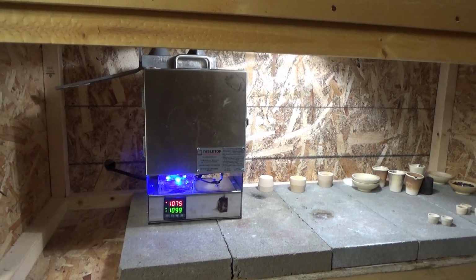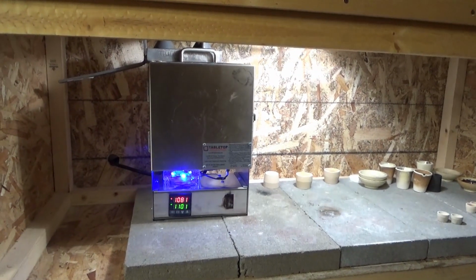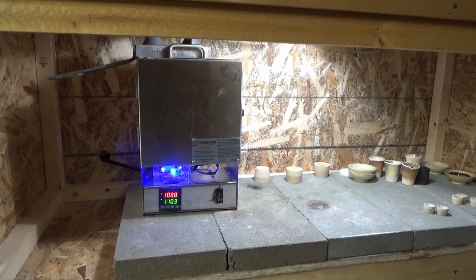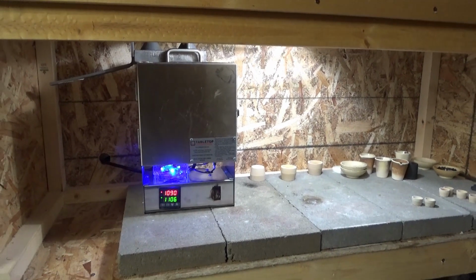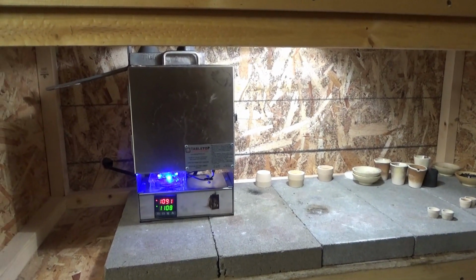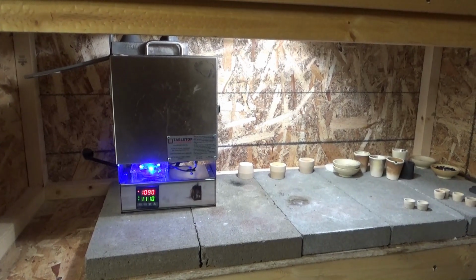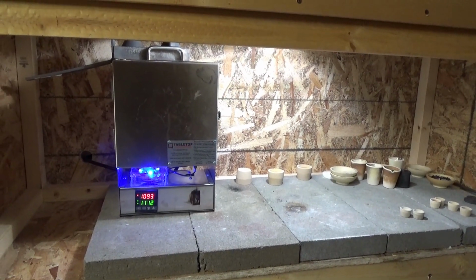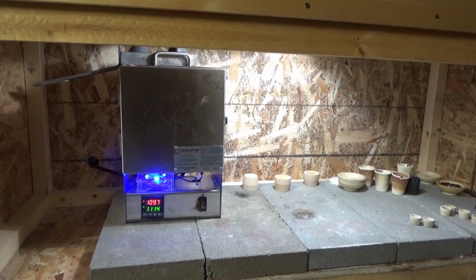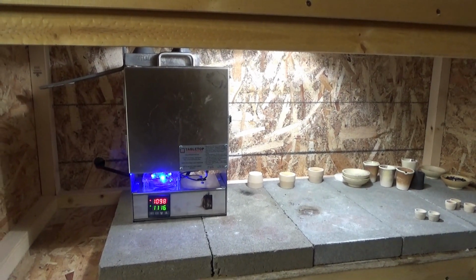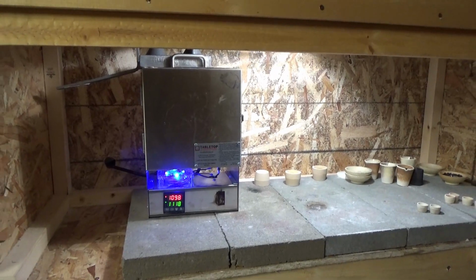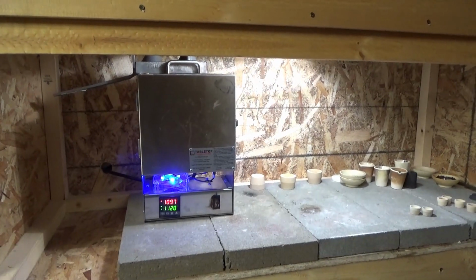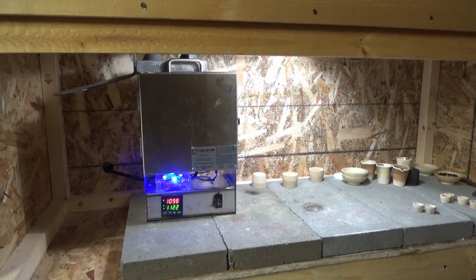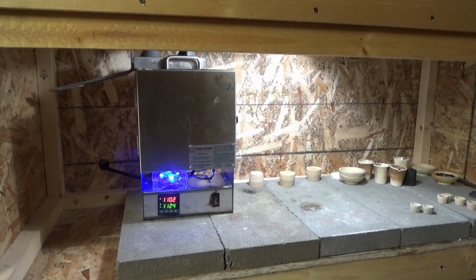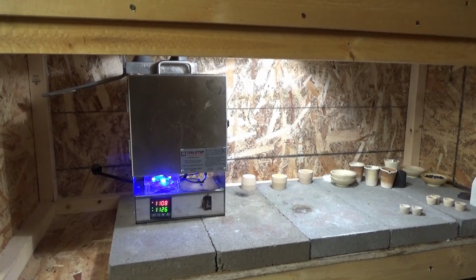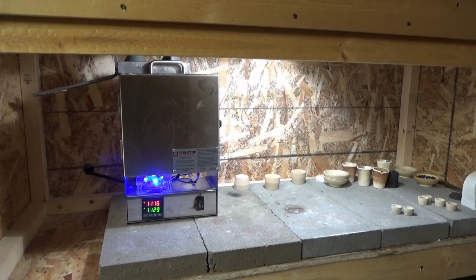And then there's the energy cost. I mean, right now we're running a generator. We're probably talking 10-20 bucks total energy cost for this recovery. So assuming that we use smelting to recover the gold from the resin, we're probably looking at a cost in the neighborhood of $35 to $40 a ton for the recovery, and we cannot use the resin again. So somewhere less than $60 per ounce would be the cost to recover the gold using this method from the resin. We'll see what happens here.